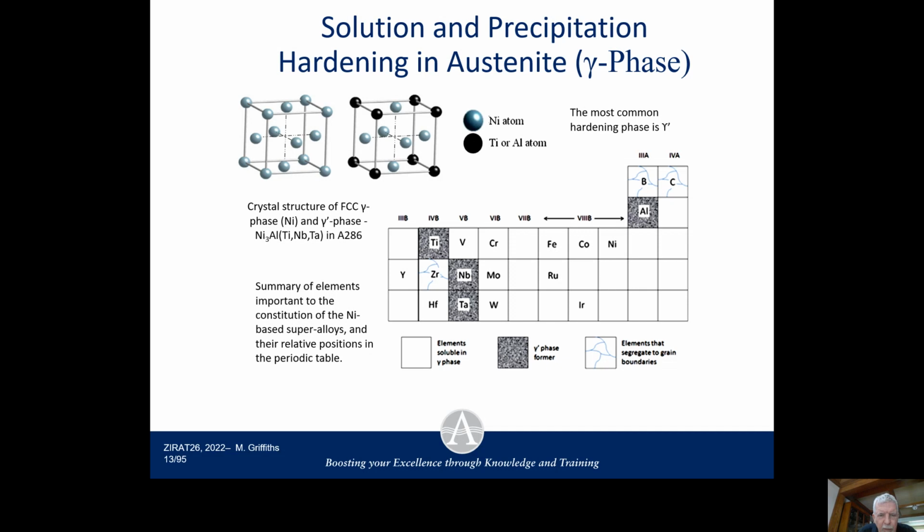Again, because by forming on grain boundaries, carbides will deplete whatever metal that they combine with, and the one that's most important is chromium. And if you form a carbide on the grain boundary, the surrounding matrix is depleted in chromium. So that can be tricky when it comes to intergranular attack, because one of the reasons that one adds chromium is that it's resistant to corrosion, but also to dissolution by solvents such as nitric acid.